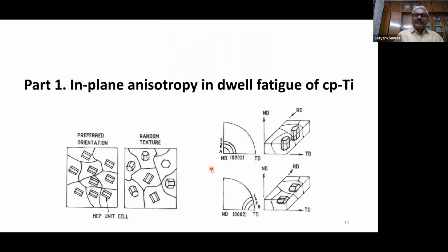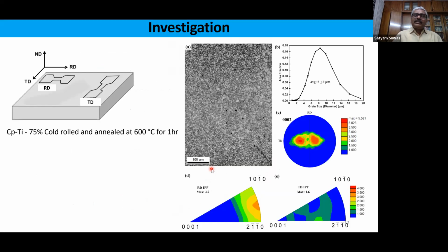So we just wanted to examine this systematically, and first we went to investigate the in-plane anisotropy of dwell fatigue. We just took CP titanium, because there has been some varying response between different alloys, and the phenomena that have been explained, or all the theories, just deal with HCP titanium. So we wanted to exclude all variables, including the presence of beta phase, which occurs in alpha-beta titanium alloys as seen in most of the investigations. So we just took commercially pure titanium and examined the fundamental aspects of dwell fatigue propensity.